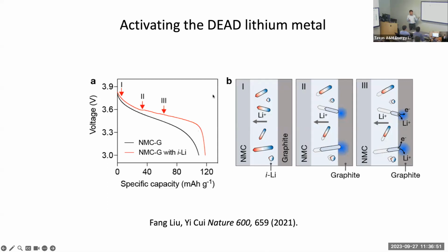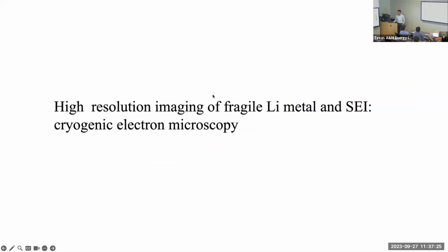After we published this Nature paper, one of my friends in Beijing told me, oh yeah, I own the fleet of electric buses from the Beijing Olympics 2008. The capacity had already decayed. After reading our publication, he asked his team to do a fast discharge for 2 minutes, and his capacity recovered by 15%. So it really helps with the fleet of buses. We proved this in our lab using a tiny cell, but in reality, the batteries also prove that. This is very, very interesting. The dead lithium is alive and can be recovered.